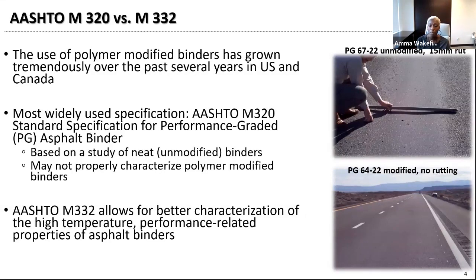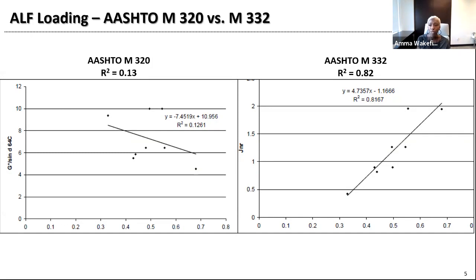67-22 unmodified in the top one, and 64-22 polymer modified for the bottom section. Now, based on what we understand about PG grading, the PG 67-22 should be more resistant to rutting compared to the PG 64-22. However, when we went into the field to do a field assessment, it showed that even with the same environmental conditions and the same traffic, 15 millimeters of rutting was measured in the 67-22 section, while in the 64-22 section, there was no rutting identified. So it's field trials like these that raise questions about how adequately the M320 is able to characterize polymer modified asphalt binders. And that's why the Institute recommends moving to the M332.